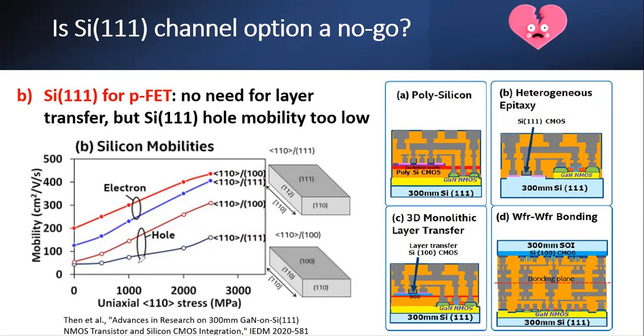But Intel found out that the hole mobility sucks. All right. The 111 is not good. Electron is pretty good, but the hole is pretty bad. And we want a good hole. That's the whole point, because we already had a good N here. Gallium nitride is a good N already. We need a good hole. And silicon 111 is simply too low for this purpose. Right. So I'm afraid the silicon 111 channel option is a no-go.